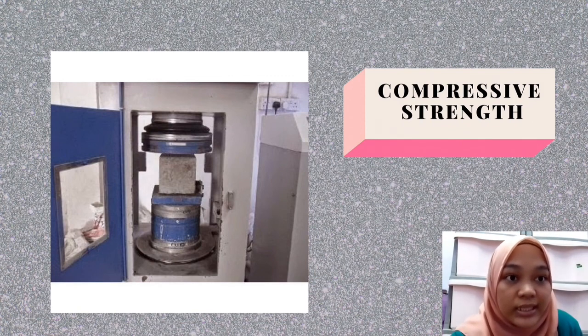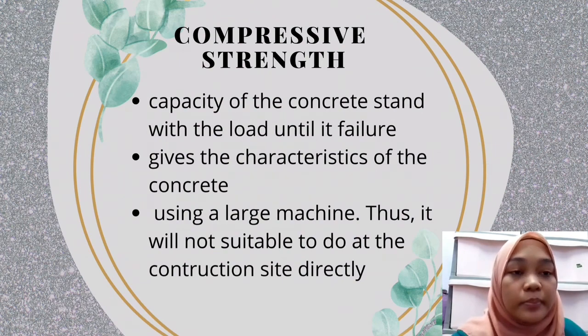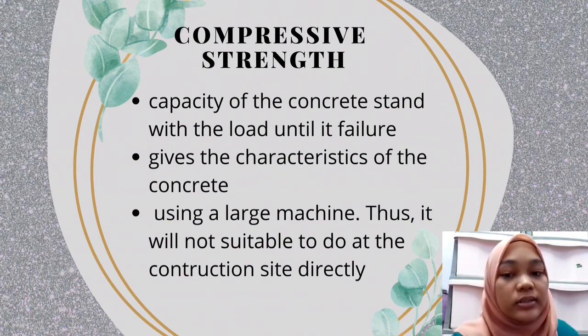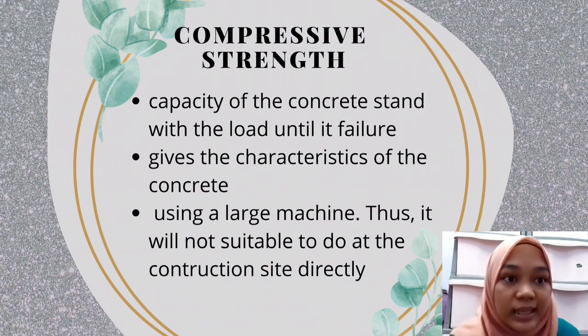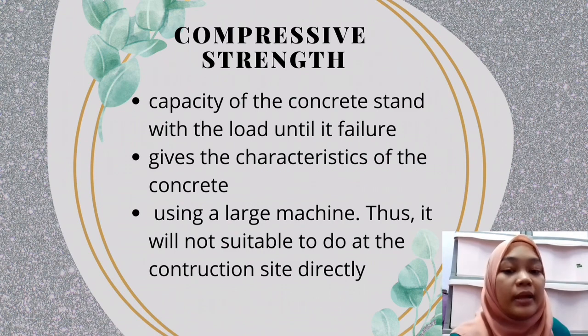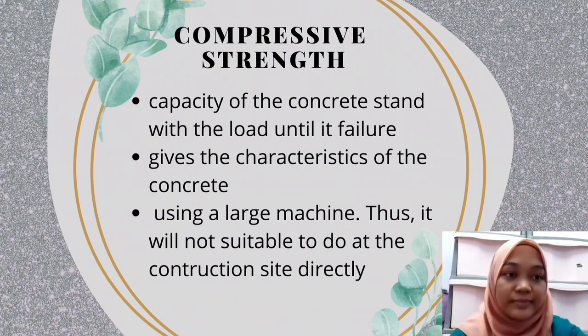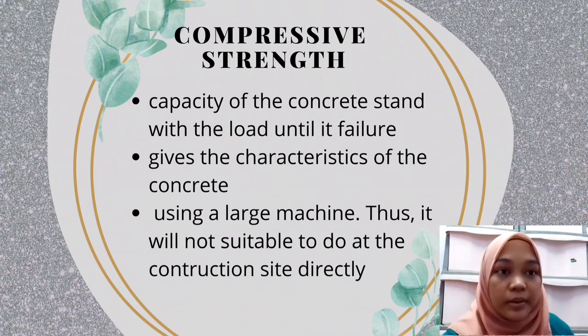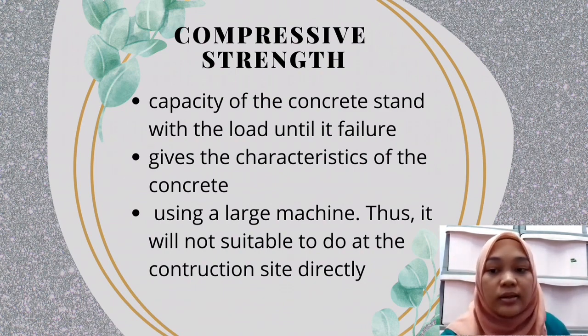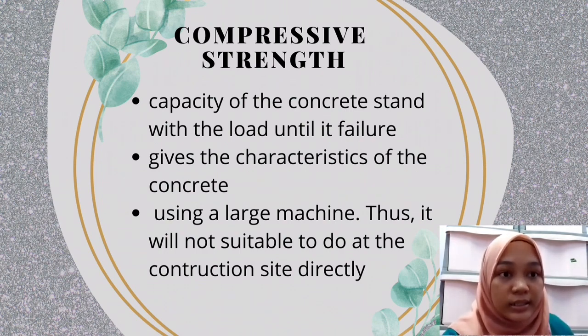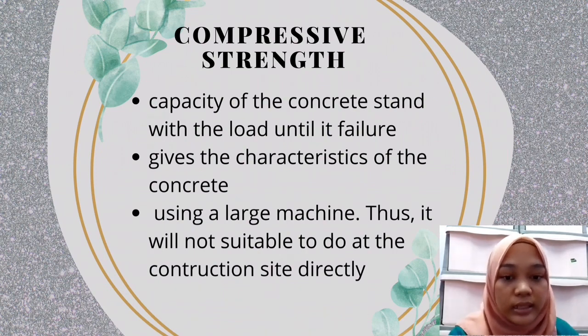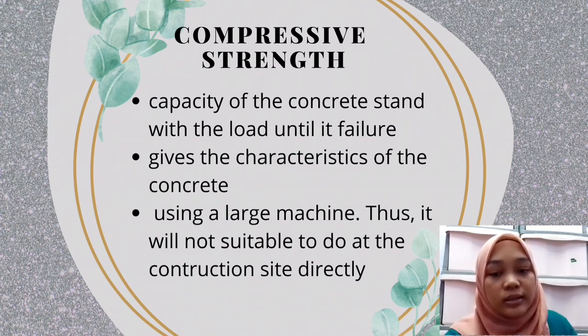And the last test used in these studies is compressive strength. Compressive strength can be defined as the capacity of the concrete to withstand the load that pushes towards it before failure. This test is very important out of the many tests applied on concrete because it gives an idea about the characteristics of the concrete. Compressive strength is measured by breaking the concrete specimens using a compression testing machine. In these studies, the compressive strength will be measured after curing time at 7, 21 and 28 days, because concrete will regain its maximum strength at 28 days.